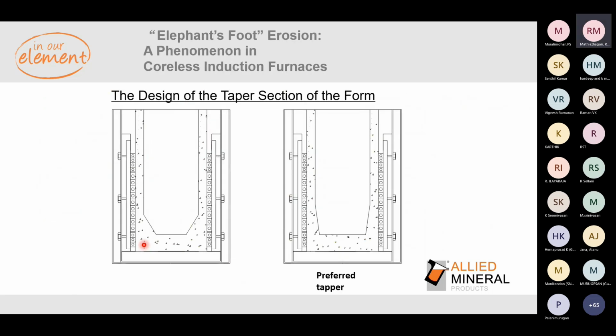So to attack elephant foot erosion, normally, with my 14 years of experience, I have seen a straight form being given by the OEMs as a regular practice, and then we convert it into a taper section. But even the taper section was not helping in the longer run to avoid elephant foot erosion. Later on it was found that this taper helps a lot, because it helps you to easily install the refractory with proper densification, and it is helping in the long run for elephant foot erosion. So this is one preferred taper when you design a form to avoid any elephant foot erosion.